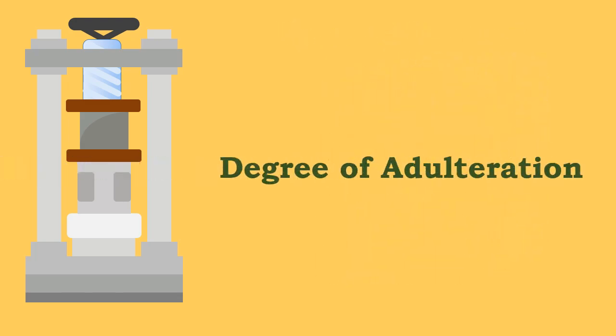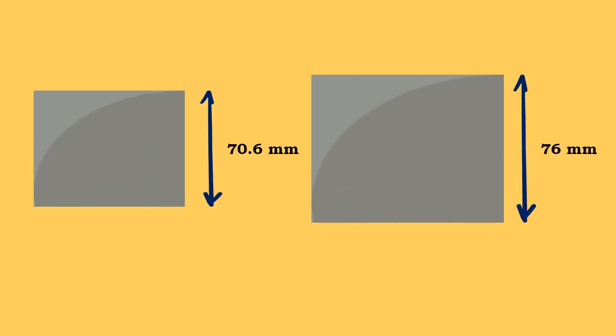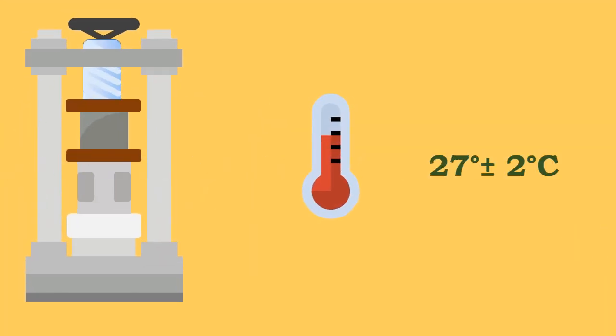The test specimens are formed as cubes with side lengths of 70.6 millimeters or 76 millimeters. Generally, specimens larger than this should not be made as cement shrinks and cracks. The temperature of water and test room should be 27 degrees Celsius, plus or minus 2 degrees Celsius.